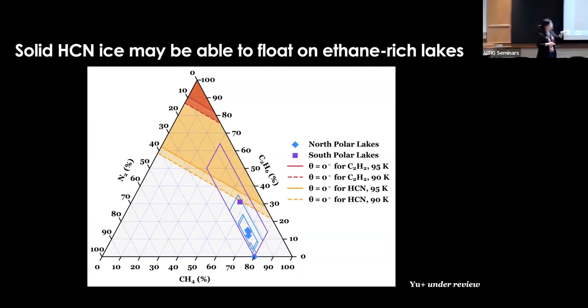So what we're showing here in the color regions is basically wherever the contact angle is bigger than 0, for the 2 species that have non-zero contact angle with ethane. And these purple and blue diamond boxes are showing you the measured liquid composition. But basically what you can see is for acetylene, C2H2, its non-zero contact angle area doesn't have any overlap with the measured lake composition. So we don't think this ice can ever float on Titan's lakes with known composition.